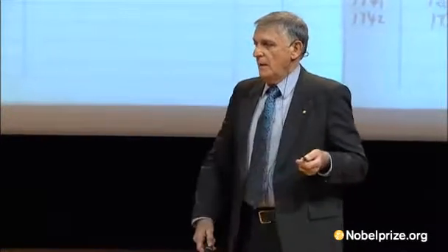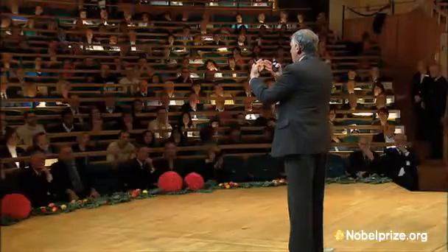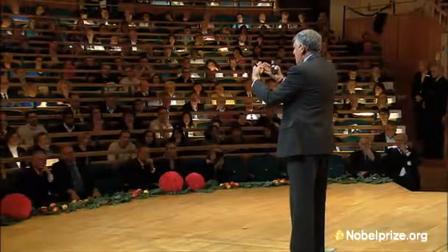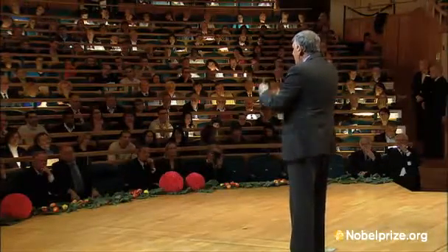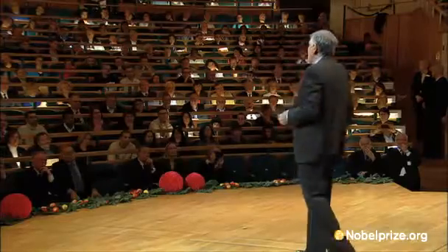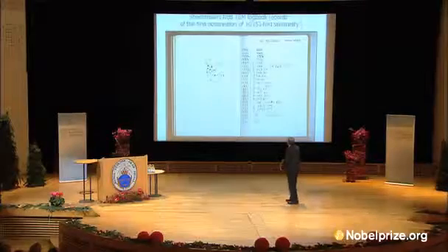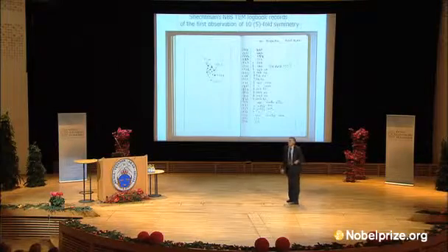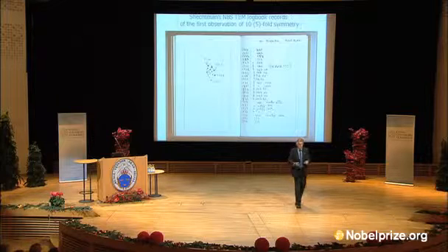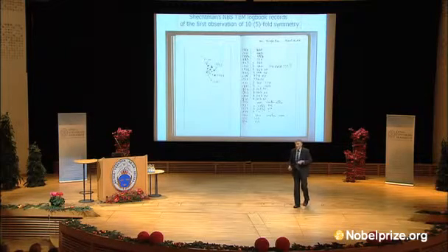And I said, okay, this must be twinned crystal. That means five crystals, which have a special boundary between them, like that. If these are atomic rods, they have a special boundary. And if you have five of them, then you have five superimposed diffraction patterns that will give you this diffraction pattern that I have seen. And I said, okay, let's find these twins. Let me just find them and forget it.